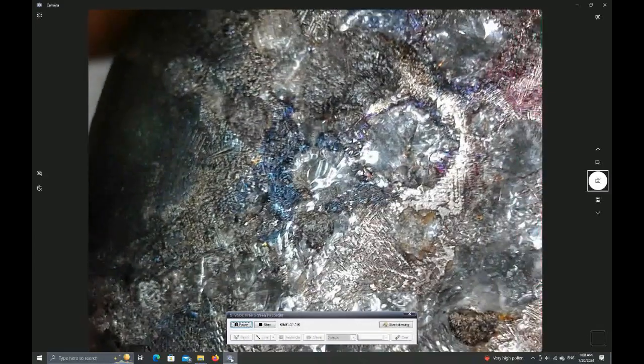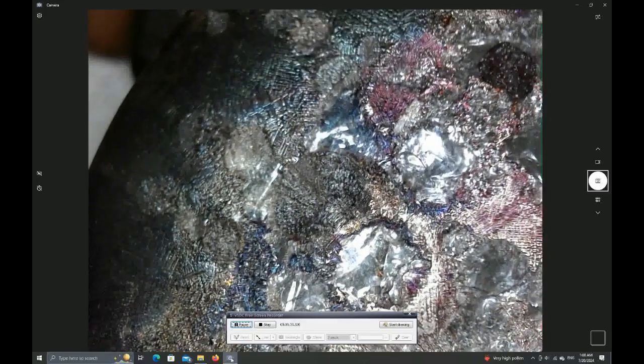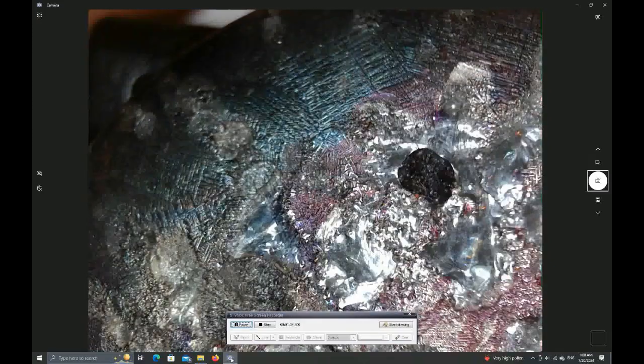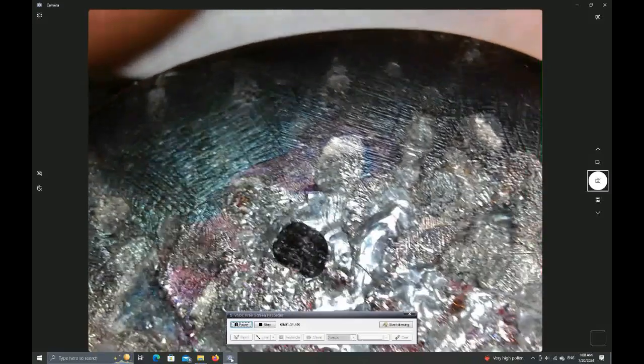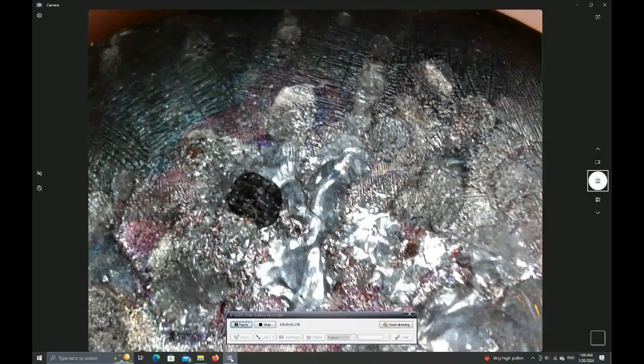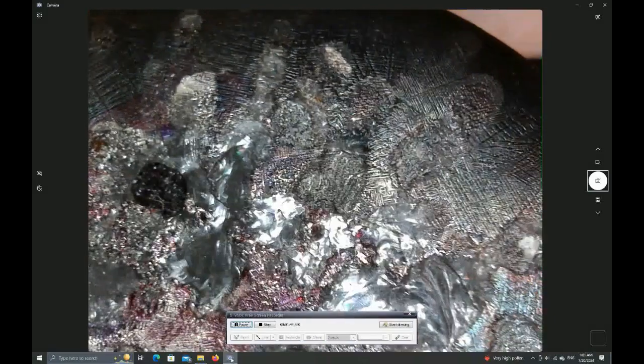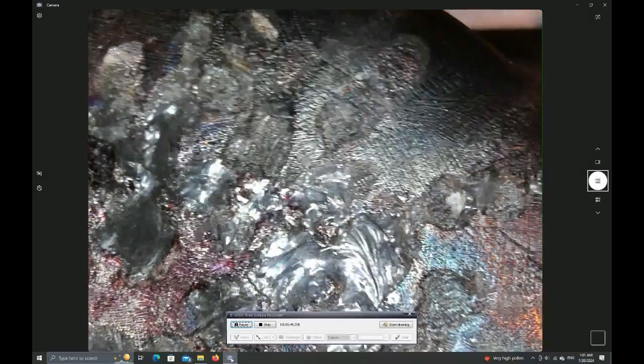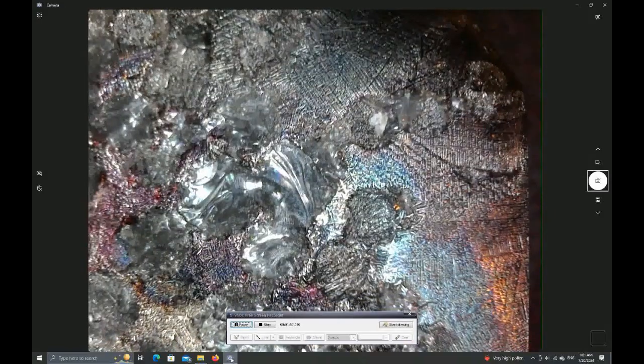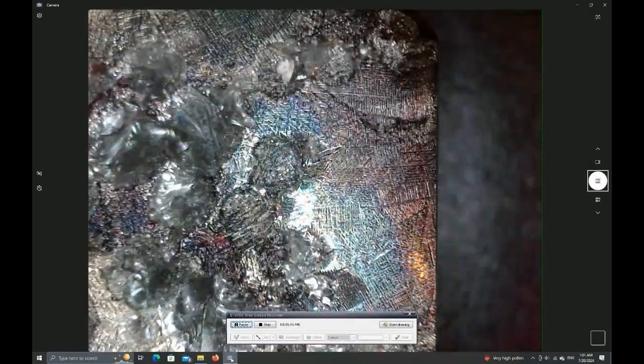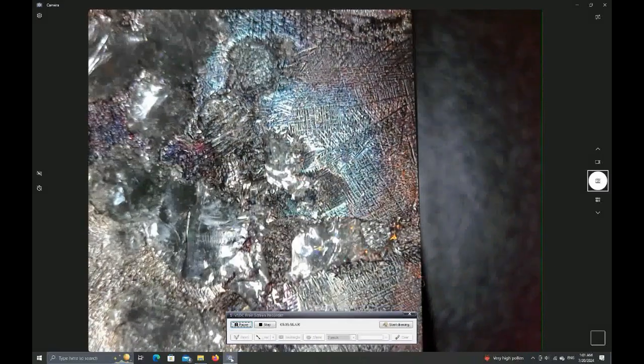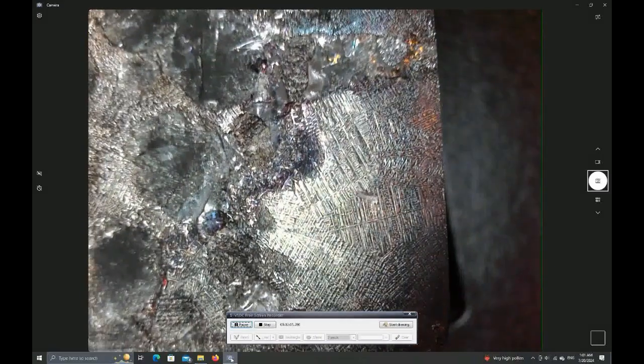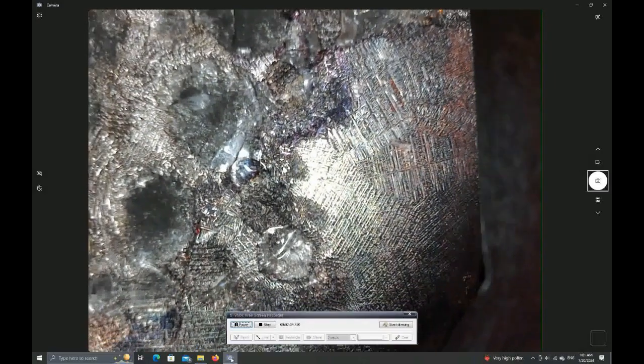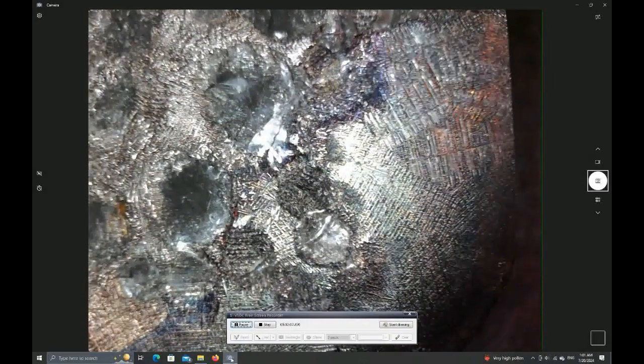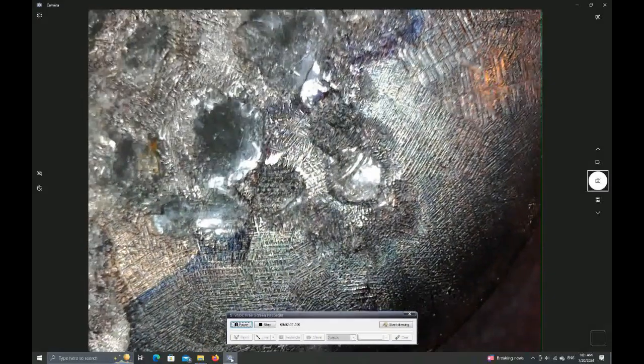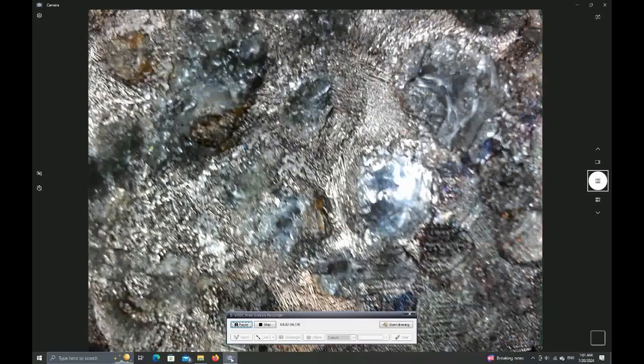However, yeah, so Spencer on Heavy Forge, his Wootz ingots will look way better than mine. Way more prominent macro structures that are easily visible with the naked eye holding a finished knife, because those 4-pound ingots, that's 4 pounds of steel mass, which is going to take a very long time to cool down, a very long time to phase transition from liquid to solid. And so he's going to have way bigger structures than I'm going to have, at least as long as I do it in an induction forge, where it's going to be cooling down immediately, because the induction forge inherently does not have thermal mass.